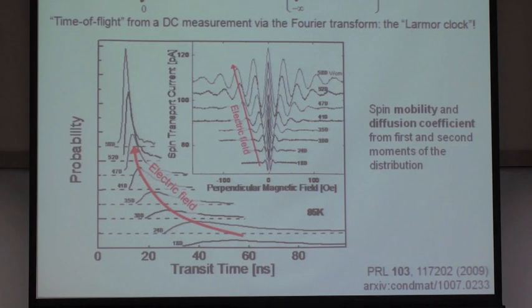The magnetic field period increases because the transit time is small. And so to get the same precession angle, you have to apply a larger magnetic field. But also, we see the fact that there's more oscillations. There's more oscillations because the effects of dephasing from diffusion are minimized.